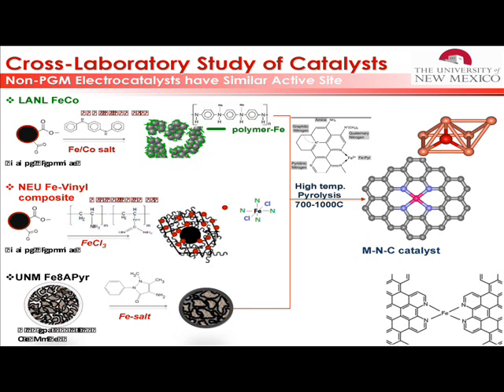And then when you do the deconvolution of the spectra with our method that is based on DFT, you see that we cannot distinguish between N2 and N3 with iron. But we can clearly distinguish an iron-possessing from a non-iron-possessing catalyst. And what I'm not showing here today is that there is a direct correlation between the catalytic activity and iron in-plane defects of these two types. And so now in San Francisco, I will bring a full paper about that, and I will discuss how that correlation about in-plane defects is important.